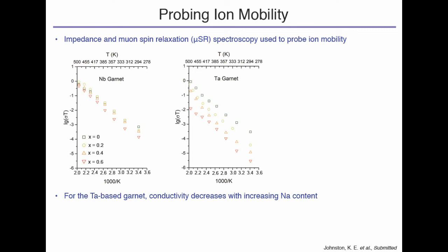What we find for the niobium garnet is that we do get a slight increase in the ionic conductivity at levels of about 0.2, but then it starts to decrease as the sodium content increases further. So it's interesting that the two garnets actually behave differently depending on the other cation present.